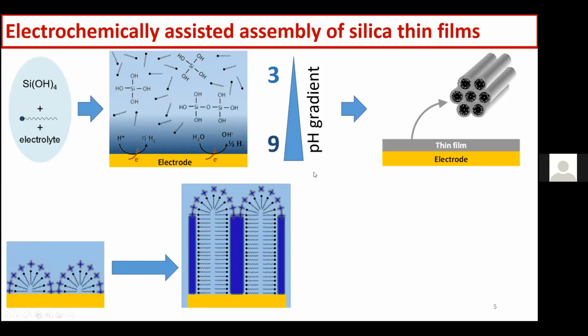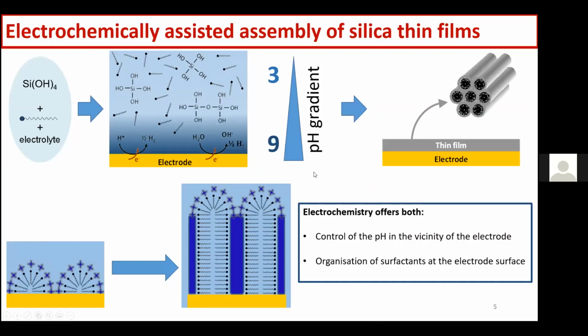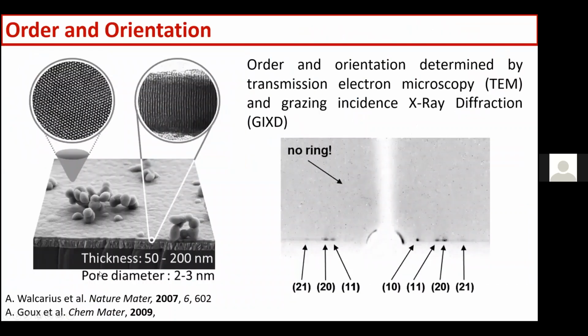From some silica beads. So in this case, the electrochemistry offers both the control of the pH in the vicinity of the electrode, which is important for the growth of the silica, and it also allows us to organize the surfactant at the electrode surface, and so we were getting the mesostructure. So this is an image of what the film looks like.